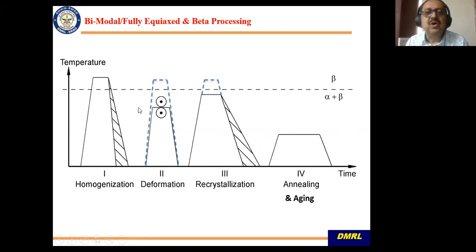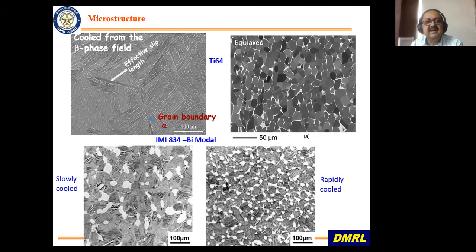Now, if you want to do a fully equiaxed or a bimodal processing of alpha plus beta alloys, after homogenization you have to give a lot of deformation in the alpha plus beta regime. You remember, to break up the alpha lamellae so that you can globularize it, and then recrystallization slightly higher than the deformation region, and then finally aging, similar aging. So depending on the cooling rate after the recrystallization heat treatment, you can get either an equiaxed microstructure or a bimodal microstructure. If you cool fast enough, you will get a bimodal structure. If you cool very slowly in the furnace, you will get an equiaxed kind of microstructure, which is good for formability application.